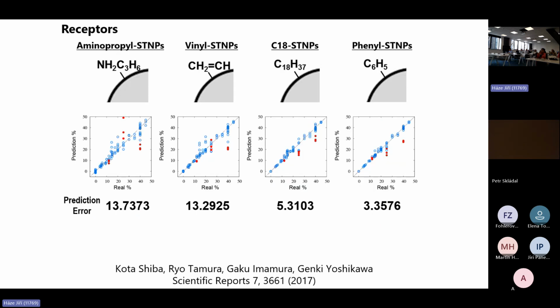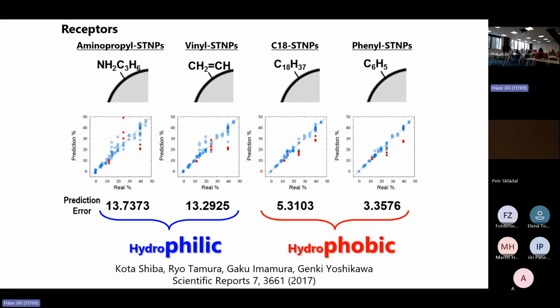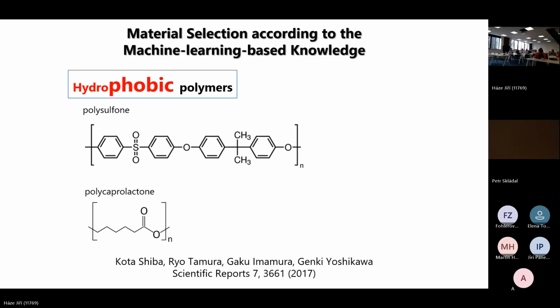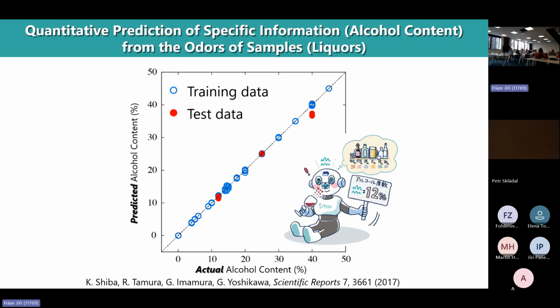So with these features, we made a machine learning model and evaluated the prediction error. As you can see, these 2 materials have a big prediction error, but these 2 have a low prediction error. In this case, these are hydrophobic materials, and these are hydrophilic materials. So we simply replaced these hydrophilic materials with hydrophobic polymers. And finally, we got this very clear prediction model that can predict the quantitative amount of a specific content, in this case alcohol, ethanol.